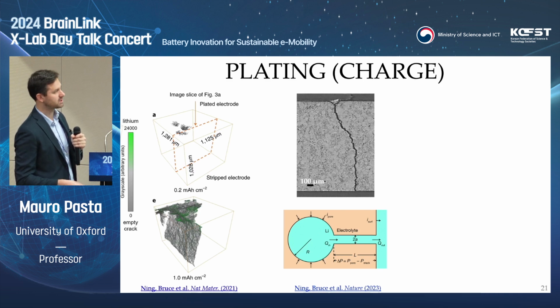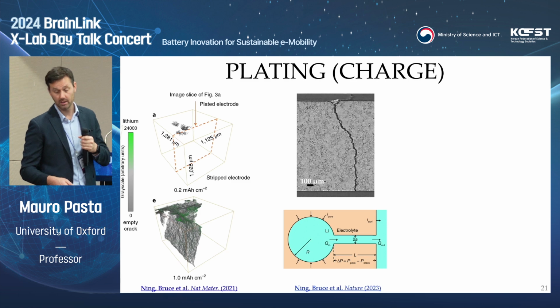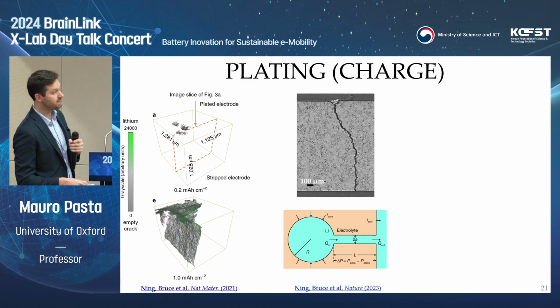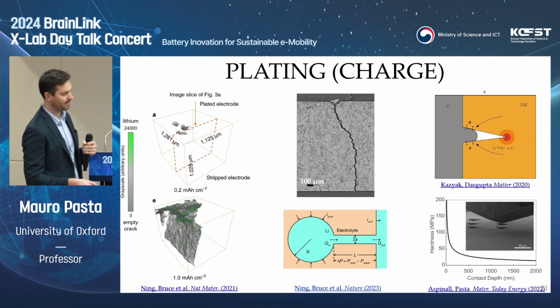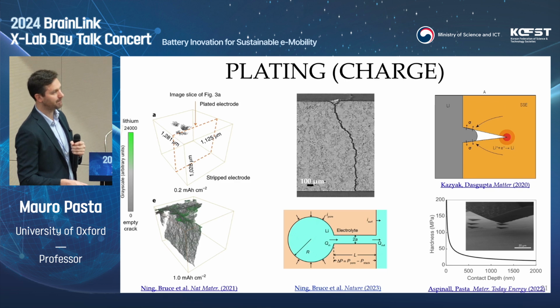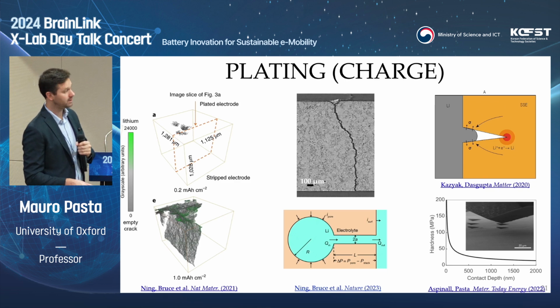And you might argue, well, how is it possible that something as soft as lithium is actually able to open a crack? Well, a couple of things. First of all, very often these solid electrolytes are very hard to densify, so they're not fully dense. There's quite a bit of porosity in there, and that's affecting their fracture toughness substantially. They're not as tough as you would think they are, and therefore a lower stress than you would expect is enough to open this crack. The second thing to consider is that for any metal at the nanoscale, its hardness is a function of the size of your defect, because the number of dislocations is limited. So lithium gets quite hard at the nanoscale. The combination of both the presence of defects and the mechanical properties of lithium results in the opening of a crack that is then backfilled by your lithium.